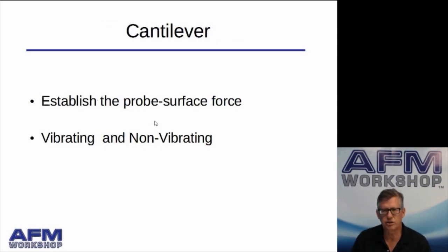So the first thing that you need to be familiar with is cantilevers, and that's one of the parts of the product that you purchase. The cantilever is important because it establishes the probe to surface force, or actually the pressure of the probe onto the surface. When you look at cantilevers, they fall into 2 general categories: vibrating and non-vibrating. People call vibrating tapping, intermittent contact, non-contact, near contact. There are a number of different trade names that are used for vibrating, AC modes. And non-vibrating is when the cantilever is not vibrating, and that's often called contact mode.